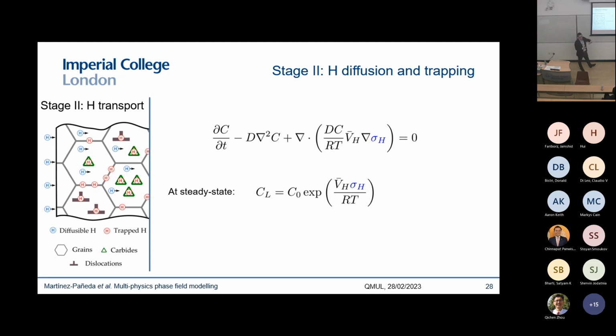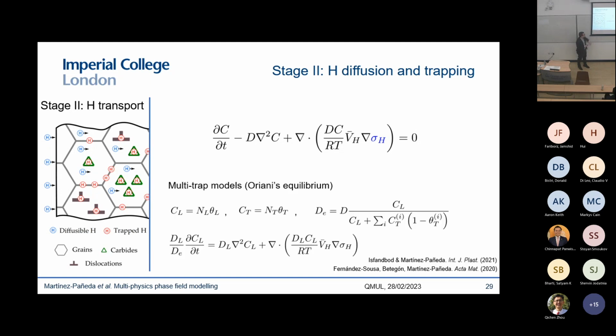And as you know, what this means is that you're going to have much higher hydrogen concentrations ahead of cracks or other stress concentrations. And this is, by the way, the easiest way that one can simulate hydrogen uptake or hydrogen diffusion within the material. In reality, we know that hydrogen atoms not only travel freely through the crystal lattice, they're also sequestered at what we call microstructural traps, like grain boundaries, carbides, dislocations, and so on.